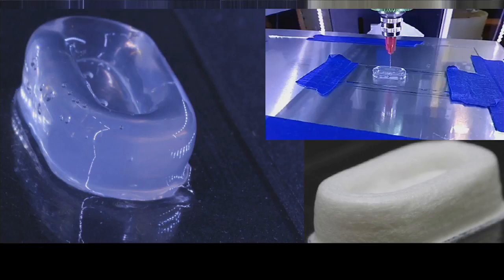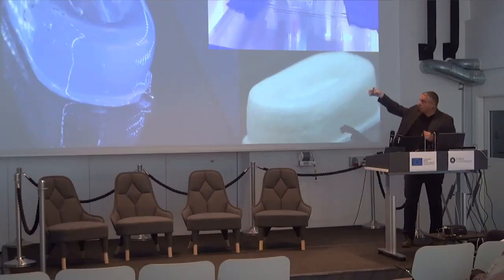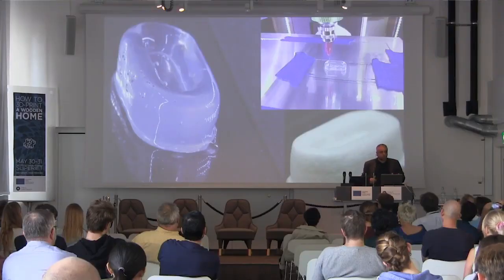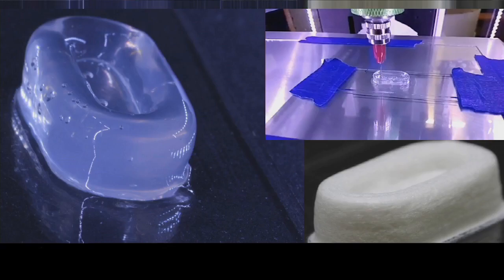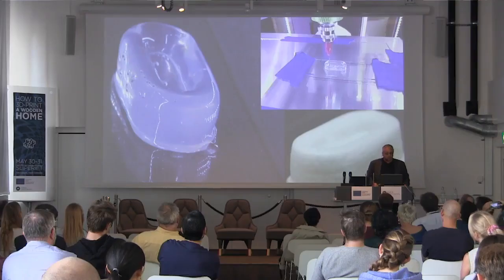Another interesting feature of nanocellulose is its thixotropic property, which brings us to 3D printing. Of course, thixotropy is a very, very important feature for 3D printing. And here we've shown that we can print practically water at room temperature. By just adding 3% of nanocellulose into water and taking an STL file of butterscotch candy, we've been able to print this candy from water. Once you remove the water, it self-assembles into this nice foam structure.